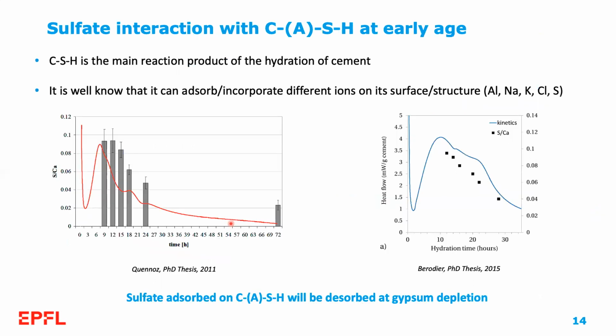And the answer to that is CSH. CSH, as we know, is the main reaction product of the hydration of cement, and it's well known that it can absorb and incorporate different ions during the hydration process, particularly sulfate, that as we are concerned here, but it can also incorporate things such as alumina, alkalis, and chloride. We can see here from previous work in our lab that the amount of sulfate in the CSH is very high before the aluminate peak, and then it decreases as the aluminate reaction restarts after depletion of solid gypsum in the system. So basically what this shows us is that sulfate is absorbed on CSH and then is desorbed at gypsum depletion.